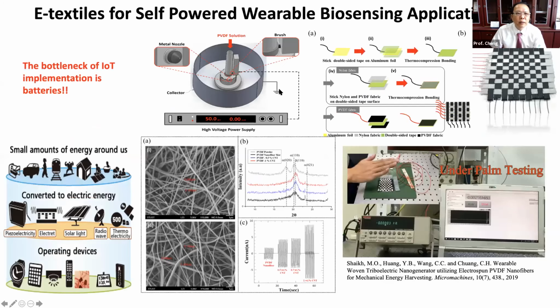And the last part of my talk is we also developed an e-textile. For the e-textile, we try to use PVDF fiber. This PVDF fiber is made using an electrospinning machine. We designed this electrospinning machine. We have 10 nozzles, and we can use rotation to collect the sheet of PVDF fiber. And in this PVDF fiber, we dope CNT inside. So we have carbon nanotubes inside the PVDF fiber.